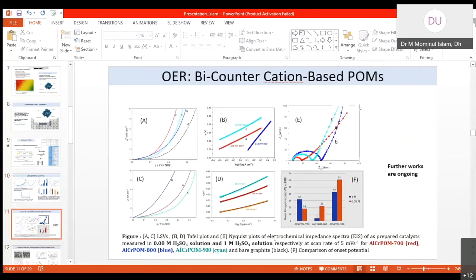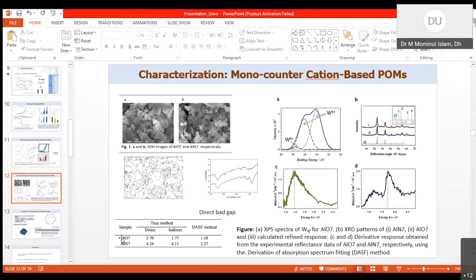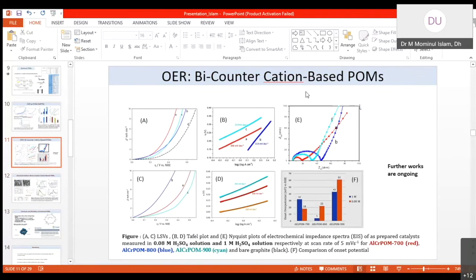And then we have been synthesizing, and we are now working with a second type of catalyst, in which aluminum is partially replaced with chromium, and the polyoxometalate is prepared this way to get the advantage of both. And we found that the aluminum-chromium bimetallic catalyst gives a high percentage of oxygen evolution.